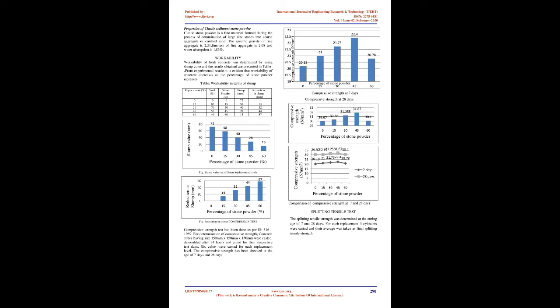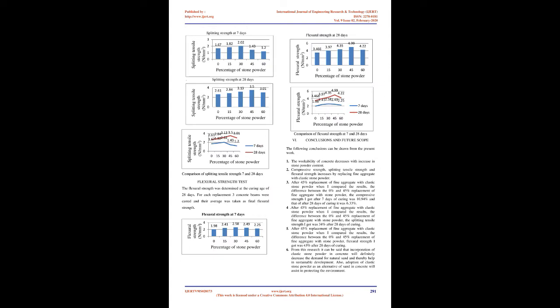For determination of compressive strength, concrete cubes having size 150 mm x 150 mm x 150 mm were cast, demolded after 24 hours and cured for their respective test days. 6 cubes were cast for each replacement level. The compressive strength has been checked at the age of 7 days and 28 days using a compression testing machine (CTM). The total number of cubes cast was 60.